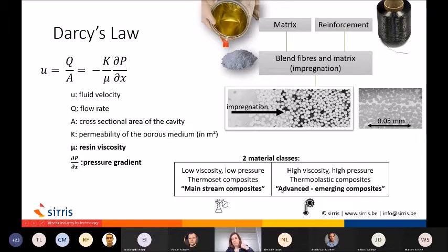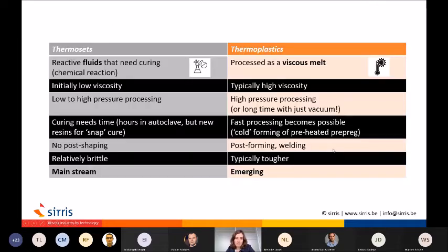When we look at what is happening today, we see more and more advanced composites where you have a high viscosity, high pressure. You also need a high temperature for these kinds of processes. So it's good to keep this in mind as I go further. We have two kinds of material classes within composites. Thermosets, where we have very fluid resins, an initial very low viscosity. During processing, this viscosity will rise in order to get a rigid structure. But initially we need mostly low pressure, but there are also processes with higher pressures.